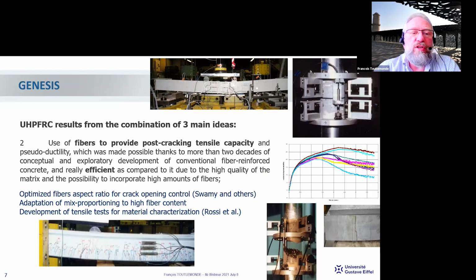But it was made really efficient due to the high quality of the matrix and the possibility to incorporate much higher amounts of fibers, typically 2 to 3 or 5% of fibers, while you are probably limited to less than 1% of fibers if you have a C40 to C80 concrete.